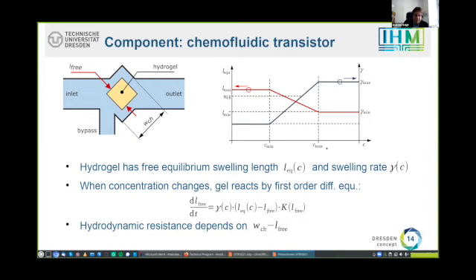And when the concentration changes, the gel will react by a first order differential equation. So the derivative of the size of the gel is simply the swelling rate times the deviation of the current gel size from the equilibrium size, times some correction factor that we learned we had to introduce. If this value l_free is bigger than the chamber size, then the transistor is blocked, of course, because the hydrogel hits the chamber walls. And if the hydrogel size is smaller than the chamber size, then the hydrodynamic resistance will depend on the difference of the chamber size and the gel size, and can be calculated by the Hagen-Poiseuille law for rectangular channels.